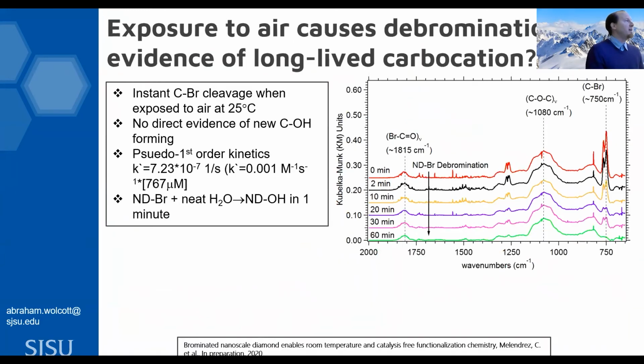And what we found is that this bromine does not want to stick around. We would argue that the bromine is so labile that it can even debrominate in inert atmosphere over a couple of weeks. So we have a window of time in which for us to use these bromines.